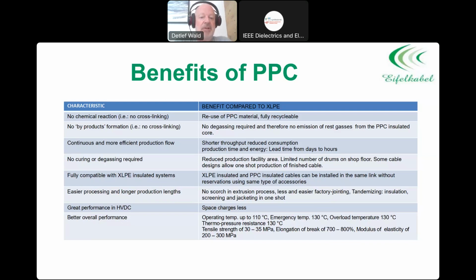The other advantage, and I think that's going more in when we're speaking about DC and high voltage application: since you don't have any cross-linking, you don't have any byproducts during production. That means you don't need to do any degassing. It's not such a big advantage for medium voltage, but for DC application it gives you a clear advantage because you can produce the cable and immediately continue, and the electrical properties do not change too much over time, except due to aging.